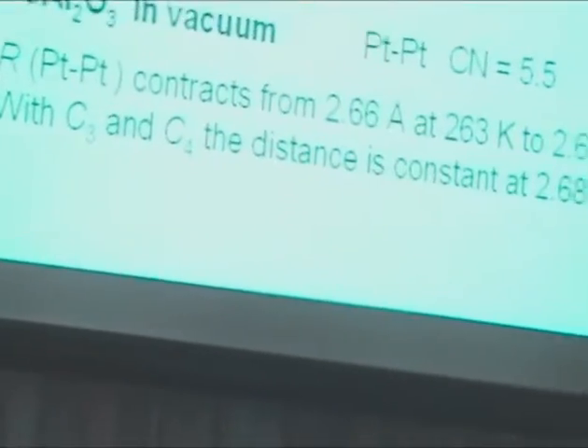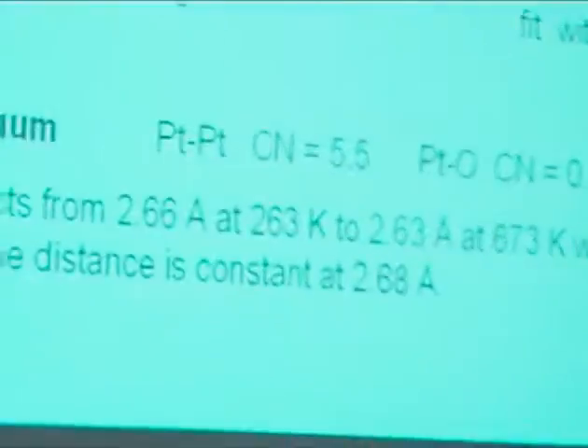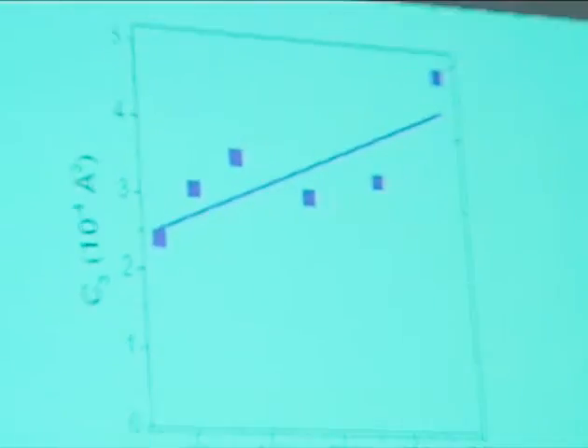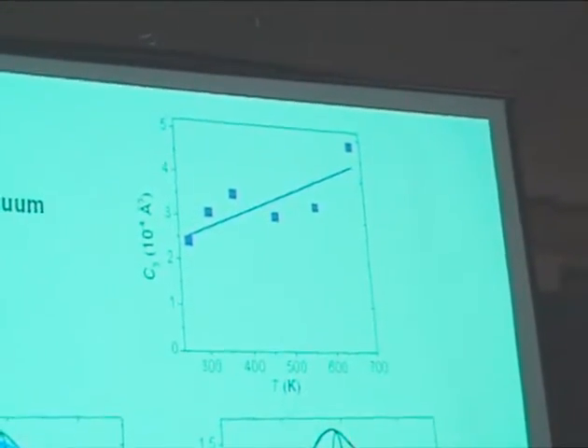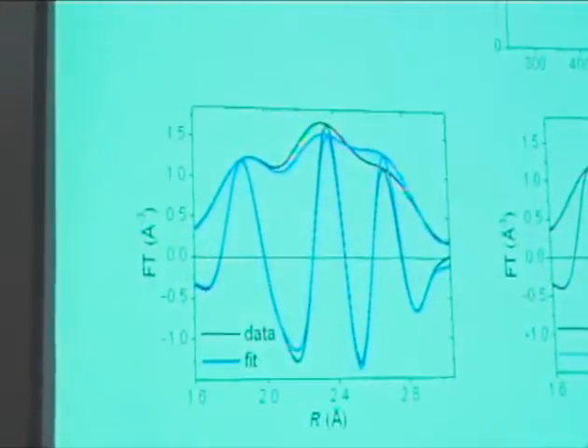My coordination number measured in the classic way would be 5.5. Remember the FCC structure of platinum, 12 neighbors in the middle there. So we are below 50%, so we really have small particles. We see even the oxygen of the alumina on which the bottom platinum is sitting. And also the analysis shows that without the higher cumulants there are deviations, whereas when we do it with the cumulants, it's perfect.